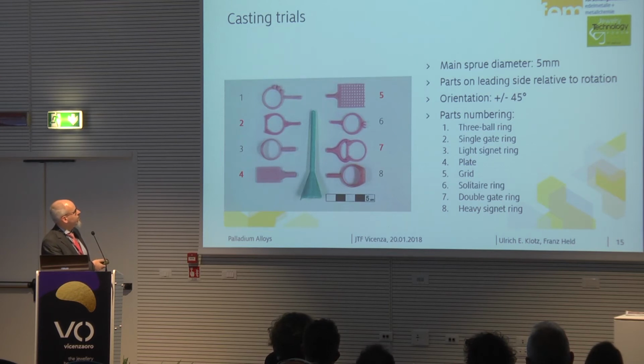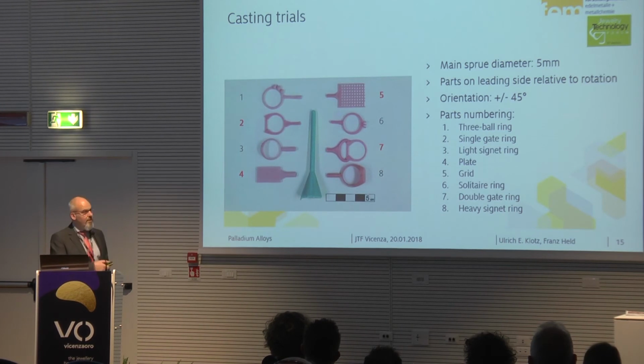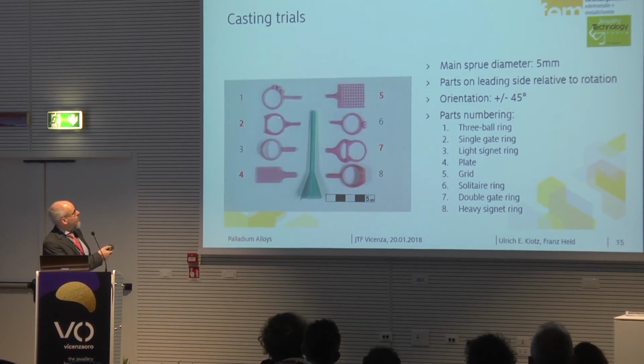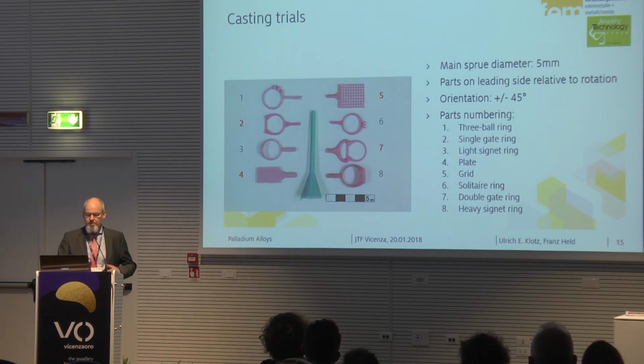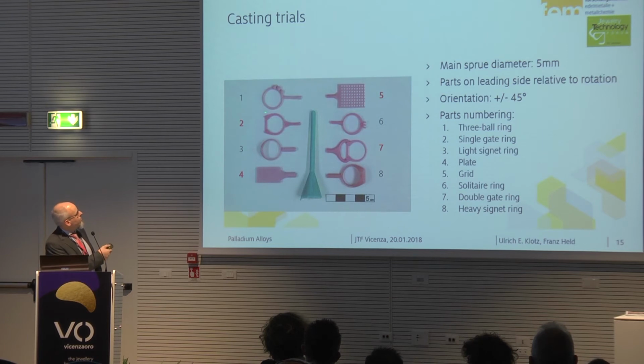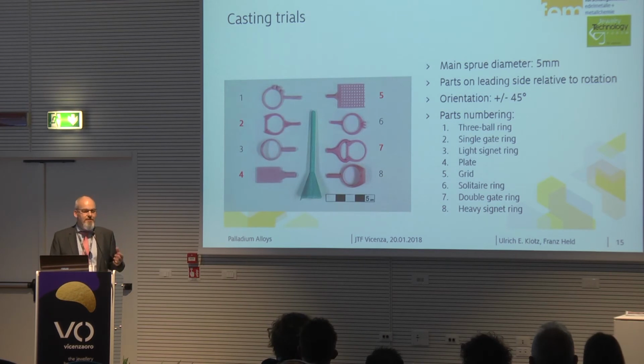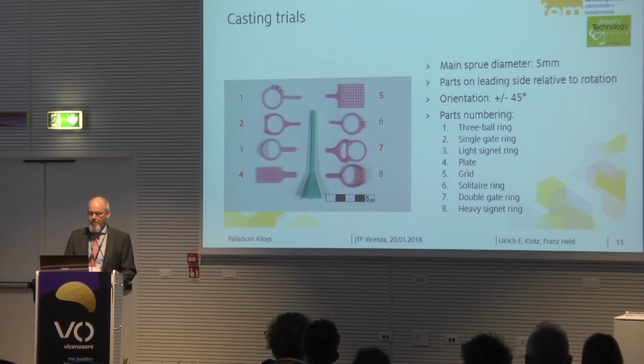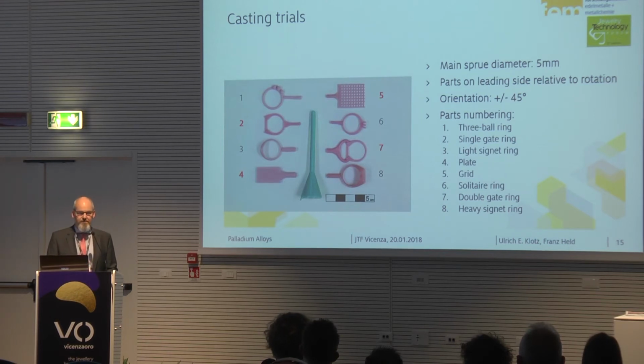This is a typical casting tree that we set out. A thin main sprue and then some standard parts like a grid for form filling, a plate for surface characterization, or these rings which are basic rings to mount setting areas for diamonds. Here in this section, we call this one the single gate ring with one gate at the thin section. And this morning you learned that this is not a very good situation because you get shrinkage porosity here. And then we had an opposite ring. We call it the double gate ring, which has sprues at the thicker section. So these are just some examples that allow us to get a principal understanding of the material.